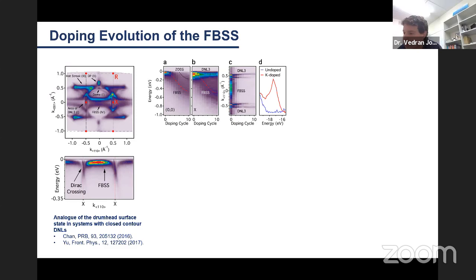And panel D shows the core level evolution before and after potassium doping. With respect to before doping, the post-deposition Fermi surface reveals a broader and fuzzier spectral weight. But even though the bulk derived contributions related to the third Dirac nodal lines and the hotspots remain intact, the flat band surface state disperses and then washes away.